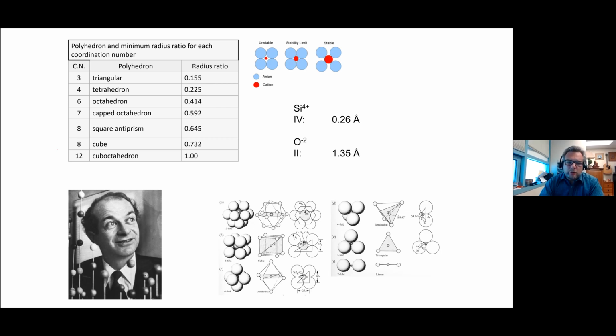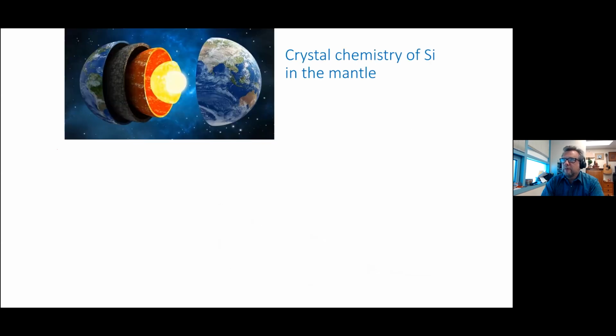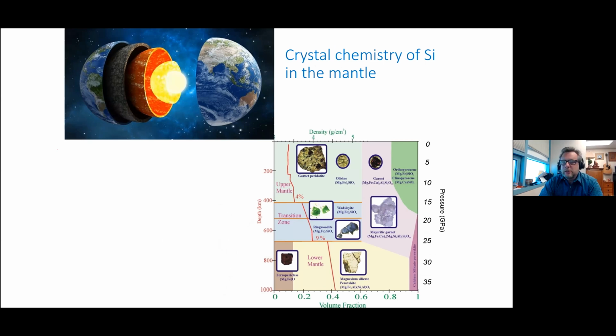If we want to understand the big discontinuous transformations that silicates undergo inside the Earth interior, we have to understand the crystal chemical trends. So Linus Pauling came up with this table of ionic radii ratios that help us to understand what is the preferred coordination number for a specific ion. For silicon and oxygen, the perfect coordination number at ambient conditions is 4. So in most of the surface silicates and shallow earth interior silicates, silicon assumes a tetrahedral coordination. However, this may not necessarily be true under high pressure. We have a number of phases that are known from their presence on the surface that have silicon in octahedral coordination, and we know that these phases form under significant pressure.